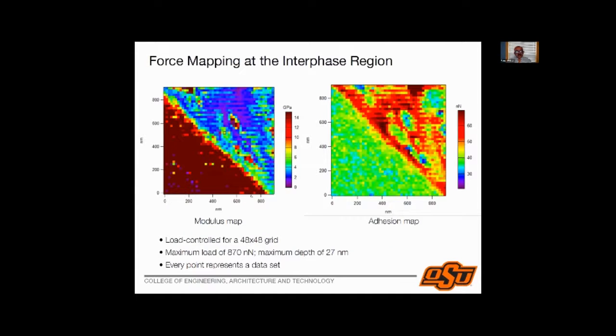This dark red area that you see in the bottom corner is part of the carbon fiber. The blue-green region is the epoxy matrix. And between these regions, you have a tiny layer, which is not the carbon fiber, which is the epoxy region, which has properties different than the bulk part of the epoxy region. So in our AFM force mapping, we go to each and every one of these points. So we have 48 by 48. We go to each one of these points and carry out an indentation experiment in which we load, we measure the displacement, and then we unload and we measure the displacement. Then we go to the next point, we do loading and unloading. We go to the next point, we do loading and unloading. So on each one of these points, I can determine the indentation response.